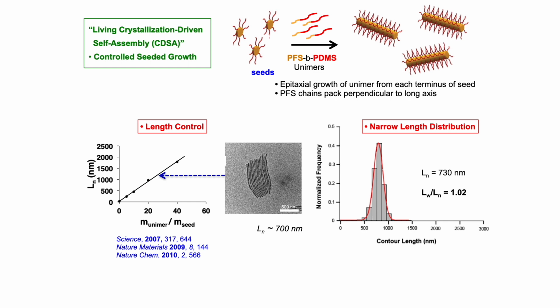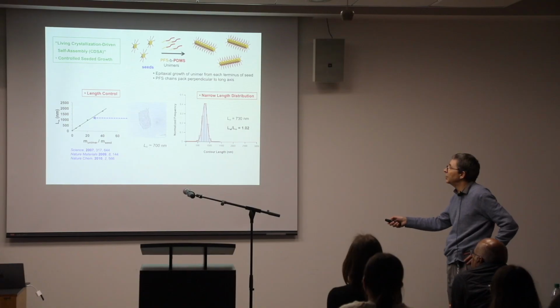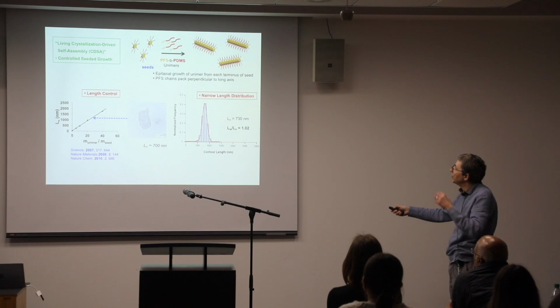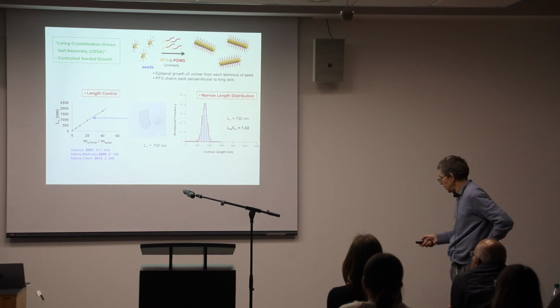If you plot the length against the ratio of polymer you add to the seed, you get a straight line, so it's a very controlled process. By choosing this ratio, you can choose the length of fiber you make, and as I mentioned, you get a very narrow distribution. You get this epitaxial growth of the unimer from the terminus of the seed, and you get growth to give you the fiber.